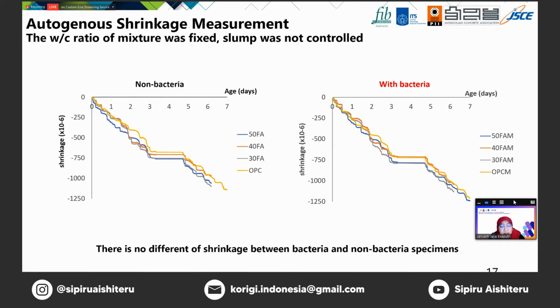We found that there is no difference of using 30%, 40%, and 50% fly ash as a cement replacement compared to the control specimens. And there is a report that using microbes in concrete, here on the right side, doesn't affect the shrinkage. So there is no difference using bacteria or non-bacteria in the shrinkage measurement.